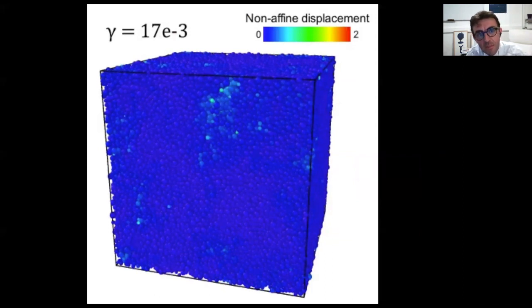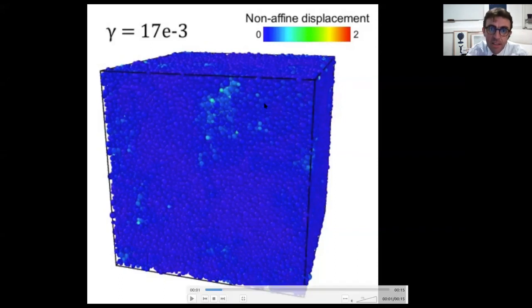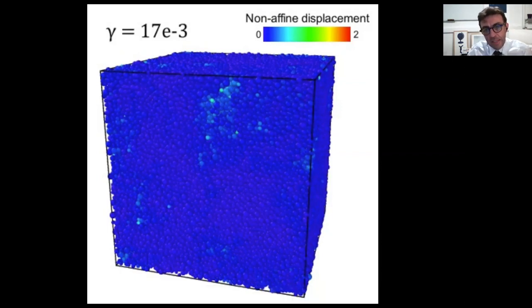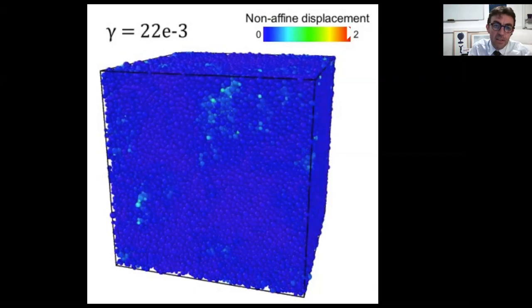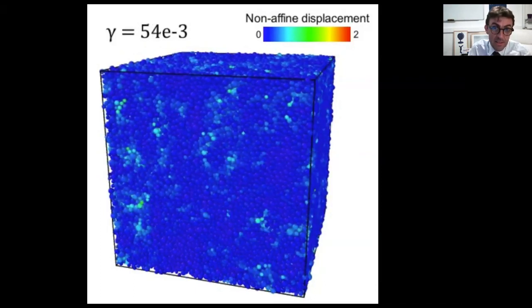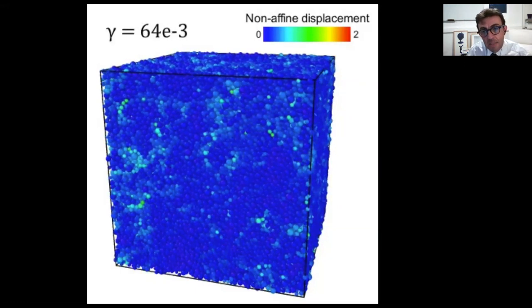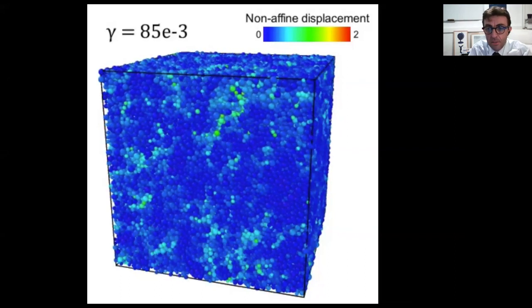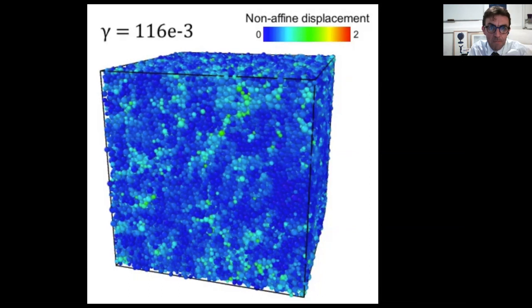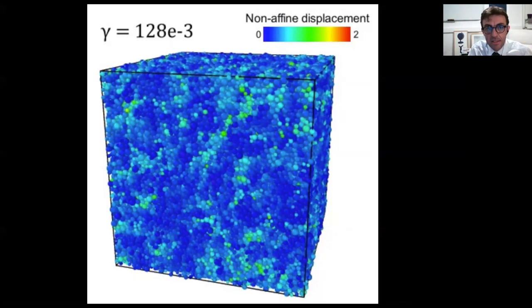So this is a computer simulation of a glass that is being deformed. The highlighted particles mean particles that have undergone some kind of reorganization in the system. And the deep blue color means that essentially the system is deforming affinely with the deformation. So if I make the movie happen and I stop it again later, you see that this system is full of defects. So there are many locations in this system where the system has reorganized. And this is allowing the slow, gradual deformation of this glass sample. So I stop again at very large deformations, and plasticity occurred everywhere in this system.